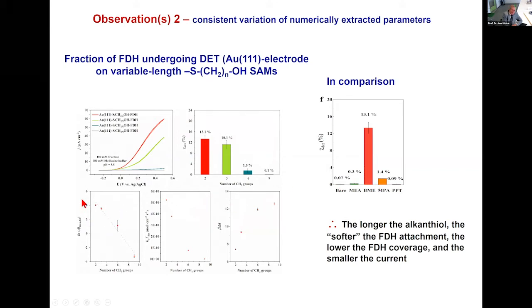So, and here are some other outcomes. Here is the current that decays approximately exponentially with increasing chain length. Here is the coverage, also strongly decreasing with increasing chain length. And then this parameter beta delta D is a measure of the extension over which electron transfer can occur. Beta is the electronic decay factor in the tunneling process, and delta D is this kind of width over which electron transfer can occur. And here you can see the longer the alkanethiol, the softer is the